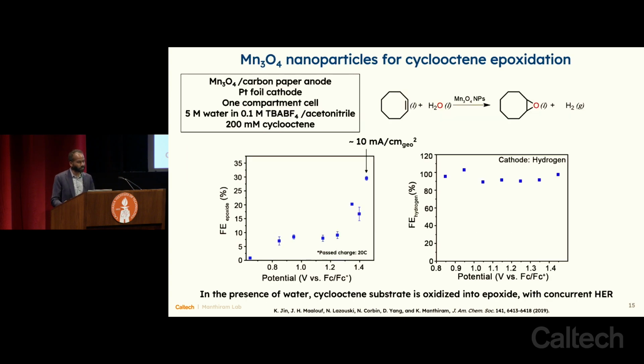So we actually found in our early work that we could reach a 30% Faraday efficiency. We were really excited to see that as a first demonstration of this reaction. We found a 100% Faraday efficiency for making hydrogen on the other side. This was initially with a model substrate, cyclooctene, just to demonstrate that this reaction was even possible.